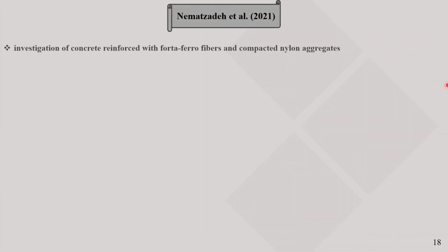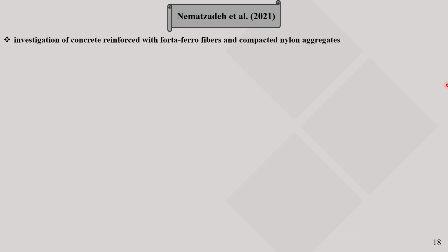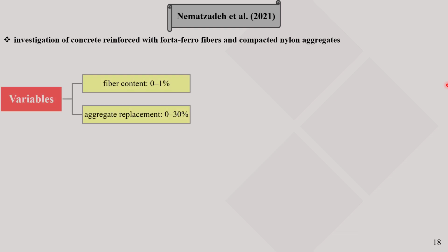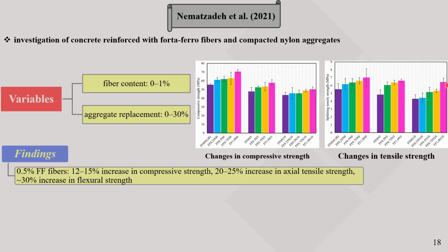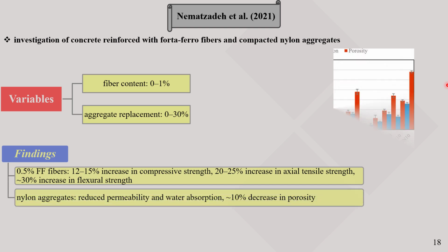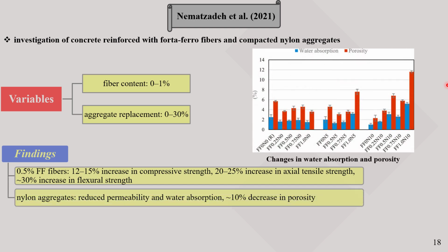Another study by Nematzadeh and colleagues examined concrete reinforced with Forta-Ferro fibers and compacted nylon aggregates. Both the fiber content and aggregate replacement ratio were varied. The key results indicated that 0.5% fiber content increased compressive strength by up to 15%, tensile strength by 25%, and flexural strength by 30%. Additionally, the nylon aggregates reduced permeability and water absorption.